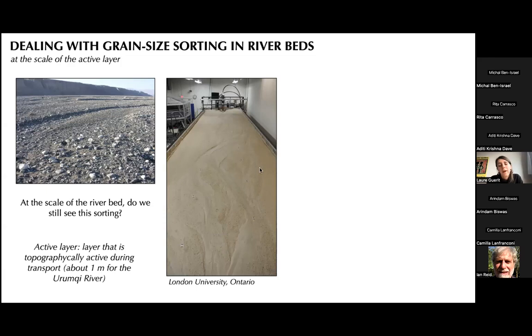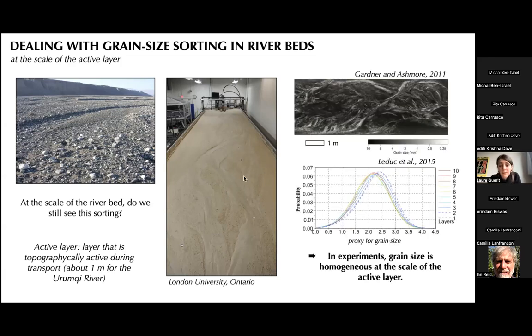So in addition to this topographic evolution, they can also record the grain size of the experiment. Here is the view from above. Black is a coarse grain, white is a fine grain, and we can observe this very nice grain size sorting at the surface of the riverbed. And these patterns are very similar to what we can observe on a natural river.